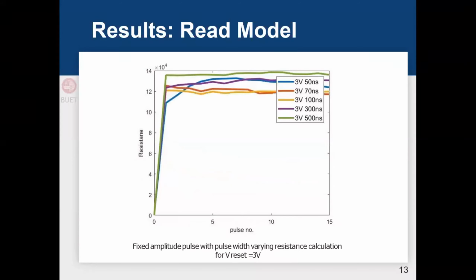And in the second case, we can also see that we are applying a reset pulse. In our experiment, we kept the set pulse voltage values in the range of 0.5 to 0.9 volt. And for the reset operation, we have kept those values in the range of 2 volt to 3 volt. So whenever we are applying a 3 volt pulse, we are actually doing the reset operation. So in this case, the 3 volt pulse is applied with different pulse widths, and the resistance is increasing as it should, because it's a reset voltage, and this high amplitude of voltage should increase the temperature so much that it will exceed the melting temperature and set the GST material to its amorphous state. So the resistance should increase, of course, but different pulse widths cause the GST to settle down to different levels of resistance.